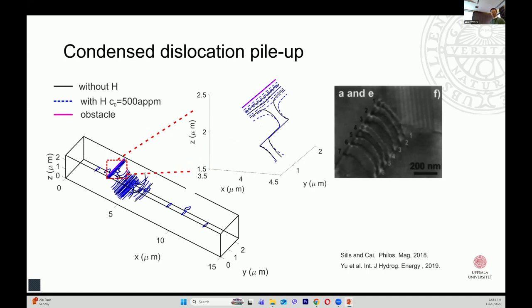And with this framework, incorporating hydrogen, we can simulate a very clean material system. This is a single crystal, and we look at a single slip system so that we can accumulate a dislocation pileup after applying load. And if we simulate the dislocation pileup with and without hydrogen and overlap these two figures together, the black solid lines represent the dislocation lines when simulated without any hydrogen. And after hydrogen is added, we get the blue dashed lines. All the other conditions are the same.